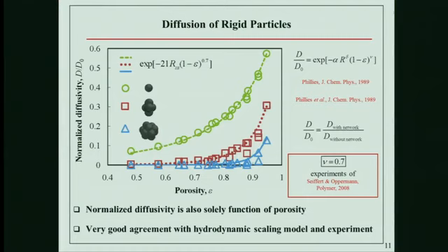Again, if we plot all the data, where each point represents a different network, we see that diffusion is only a function of porosity, same as we see in experiments. It's not a function of internal structure. Of course, that holds in the limit where the pore size is not large enough to remove the trapping effect in the network. If we go to that limit, we will see the effect of structure. But as soon as we're beyond it, they are all independent of the internal structure.